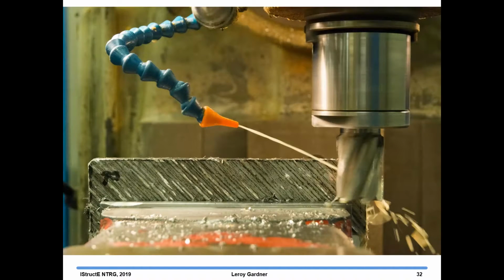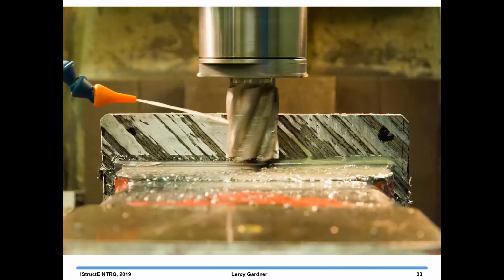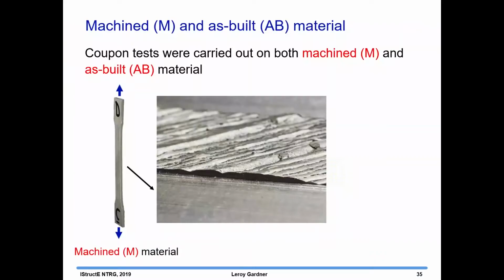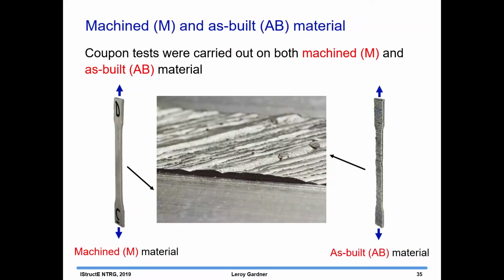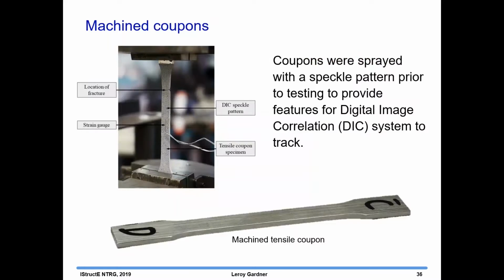We also wanted to test the material both in the as-built condition, where you had the undulating surface, but also the raw material, the smoothed down material. So we milled the as-built undulating geometry down to get a flat surface, and then we took coupons from the flat material, so-called machined coupons, and also from the as-built material. The coupons were sprayed with a speckle pattern prior to testing, and this gave us features for what's called a digital image correlation system to track during testing.